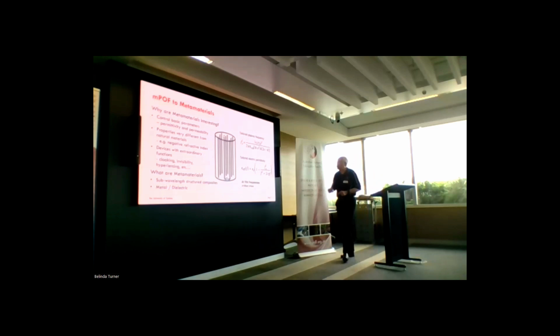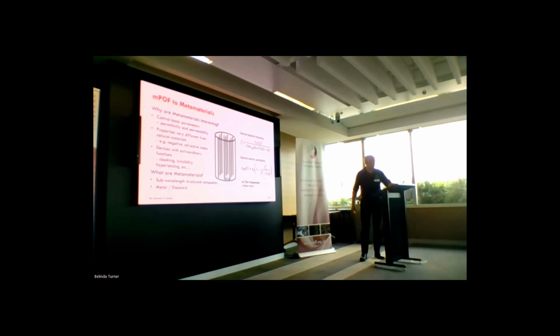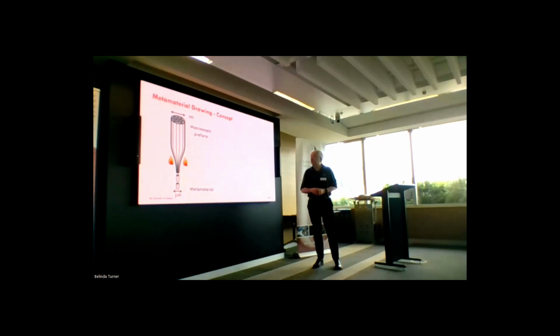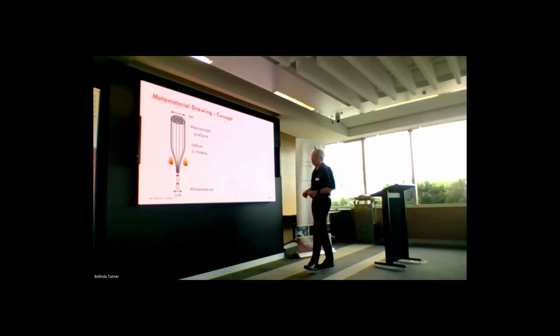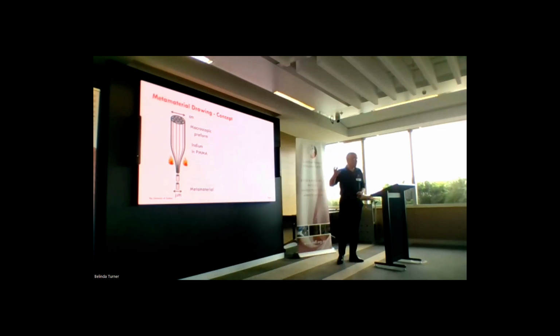And when you look at the dimensions that you can typically make quite easily in these, it corresponds to terahertz frequencies. And we heard recently why they're interesting. So our approach was to take our standard polymer microstructured fiber approach and adapt it by putting indium in the holes in a PMMA preform and then drawing it and then cutting off short lengths of it, because even though this is using fiber drawing, we're not generally launching light into it as a fiber.